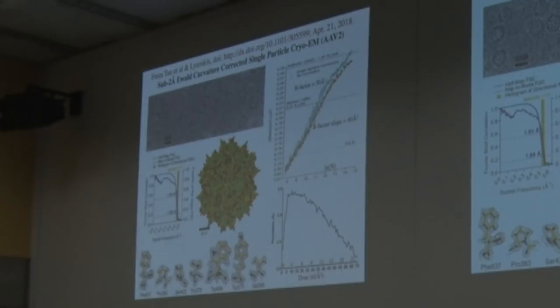And then similarly in this information versus electron dose plot, by taking all these precautions and having better grids and so on, it moved the peak. Instead of it being between 5 and 10, it's moved to the left. And that's the region where you have less radiation damage, higher quality data. But we think eventually, once it's fixed, this line will go all the way up. And so that will give you another quite considerable factor.